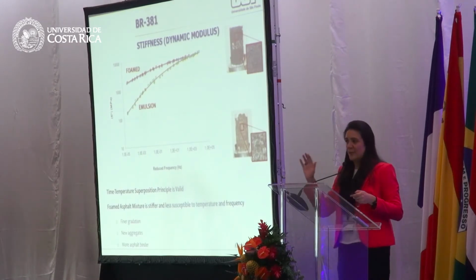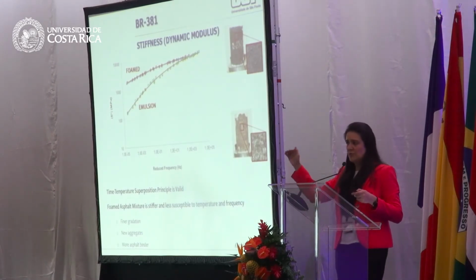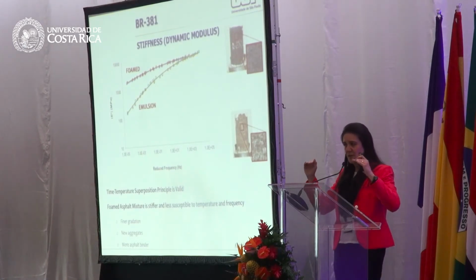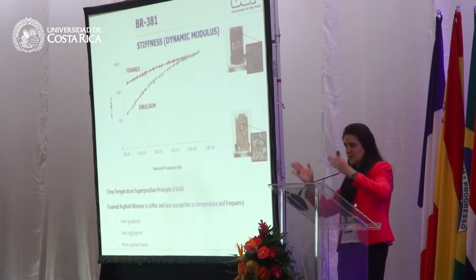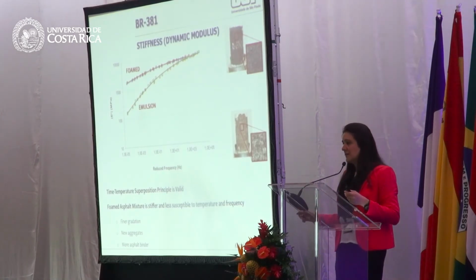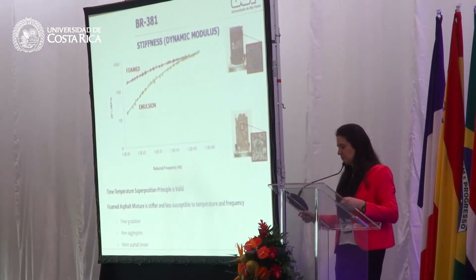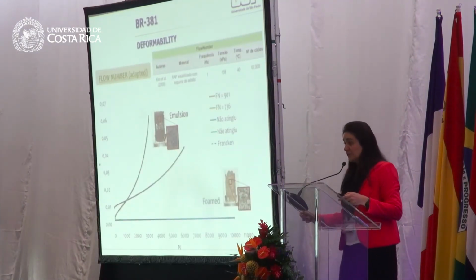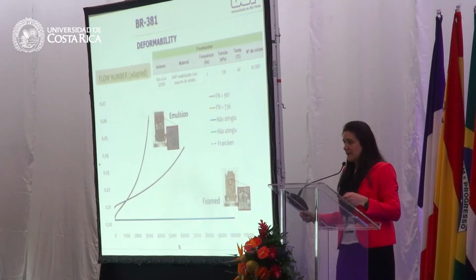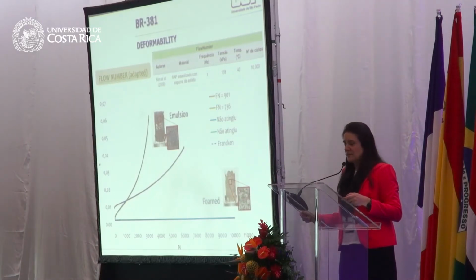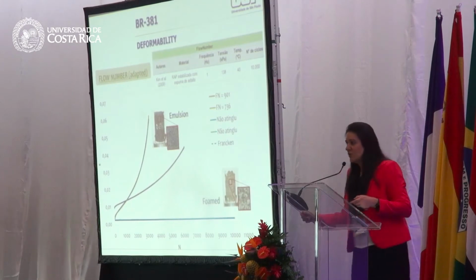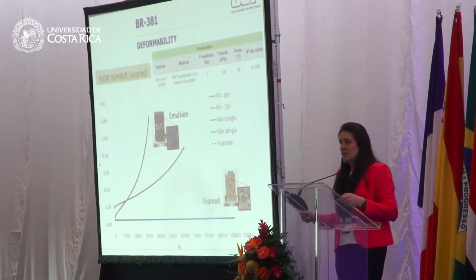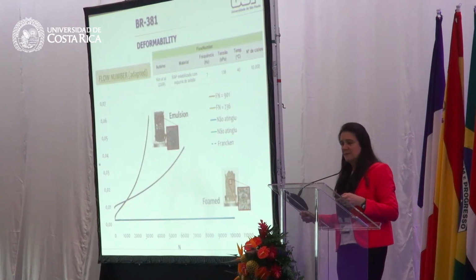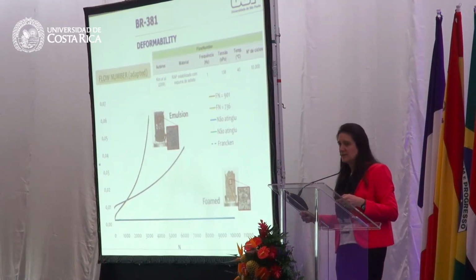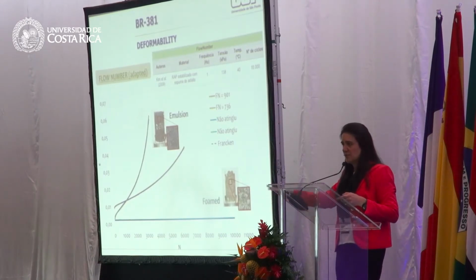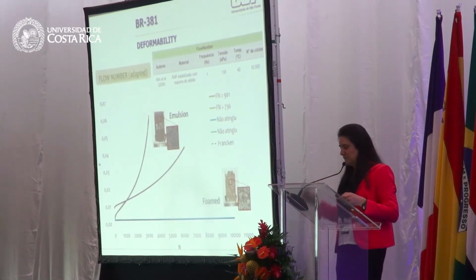So we see they are different. Although the resilient modulus is very similar, if you change from elastic to viscoelastic, we will see clearly that they are considerably different. Here are some deformation tests, and these results impressed us at the beginning, because even though the dynamic modulus is different, we ran the flow number test, and the foamed asphalt performed much better than the asphalt emulsion. And these mixtures are the same that we put on the field.